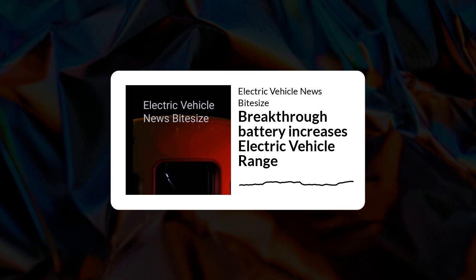The invention of the Li-S battery dates back to the 1960s, when Herbert and Ulam filed a patent in 1962, using a lithium or lithium alloy as the anode material, sulfur as the cathode material, and an electrolyte composed of aliphatic saturated amines. Several years later, the technique was improved by introducing organic solvents such as PC, DMSO, and DMF, resulting in 2.35 to 2.5 V batteries. By the late 1980s, a rechargeable Li-S battery was demonstrated using ethers, especially dioxolane, as solvents for the electrolyte. The potential of Li-S batteries has been highlighted due to scientific advances in this field.